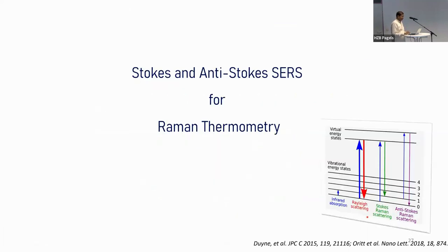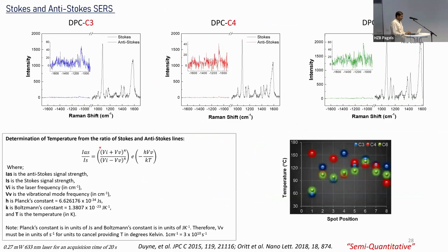So there was one technique called Raman thermometry, which is about, whenever the surface is heated, you have more population in the vibrational states, and you get a stronger anti-Stokes line. There's an equation which takes the intensity of the anti-Stokes line versus the Stokes line, and the rest of the terms are constant, and you get a temperature T. So we used this technique, but the surface temperature is even lower, 150 degrees Celsius, even by what we measure. This was one of the well-recognized techniques, but it looks like it is also not really a quantitative technique. So that's why I use the word semi-quantitative.